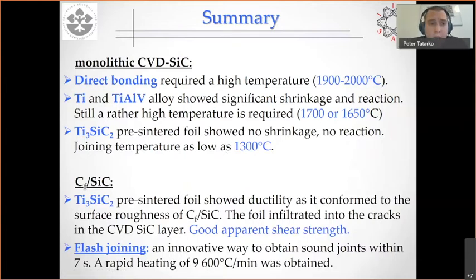So here is just a summary. I would like just a few points. I would like you to remember that in the case of joining monolithic CVD silicon carbide, direct bonding is possible. You don't need to use any metal interlayer, but you need really high temperature and pressure, and also you need a polished surface. If you use titanium, so you want to use metal-based alloys, then you can do it at 1700 or 1650, but you will have significant shrinkage and interaction with the matrix. If you use MAX phase, in terms of the pre-sintered foil, you have no shrinkage, no reaction, and you can join at temperatures as low as 1300.